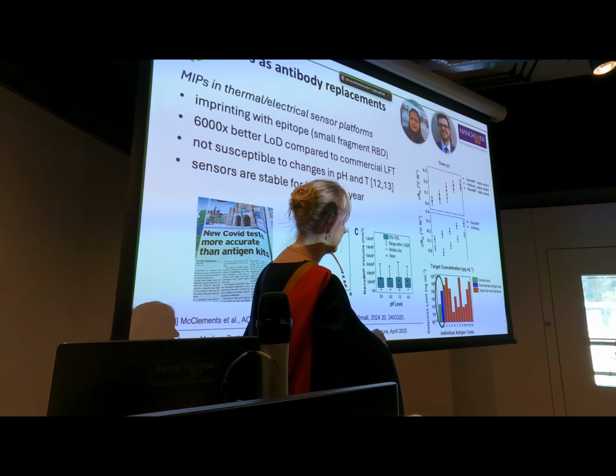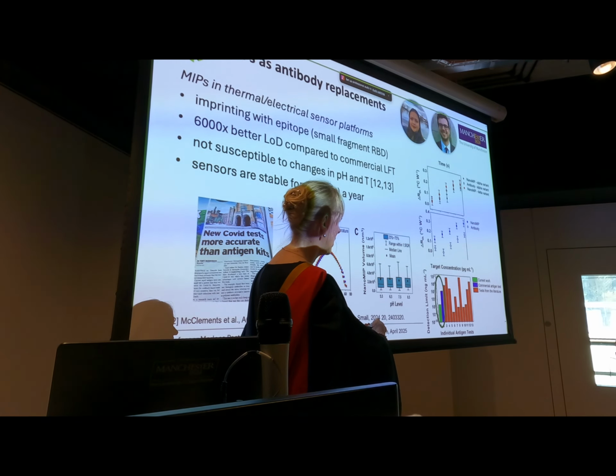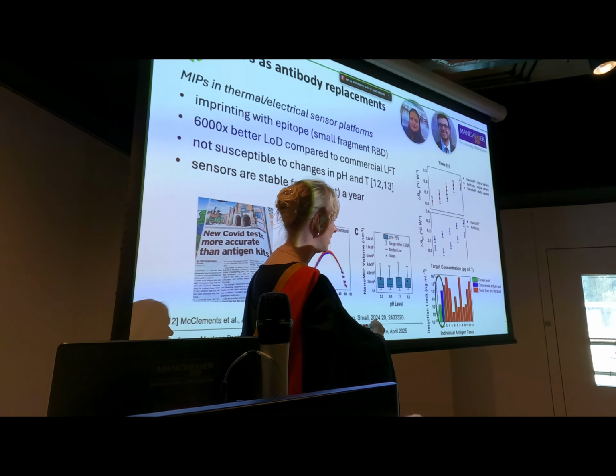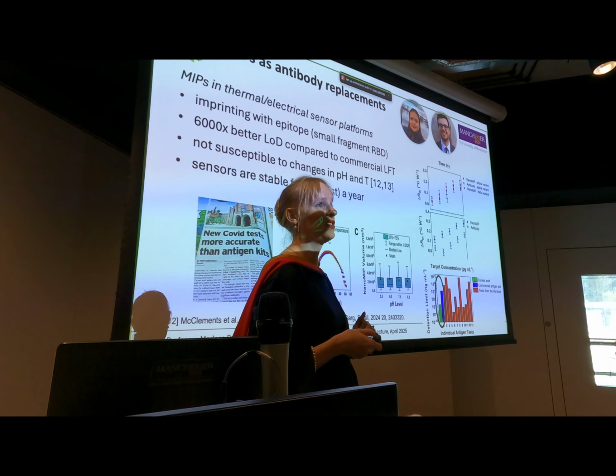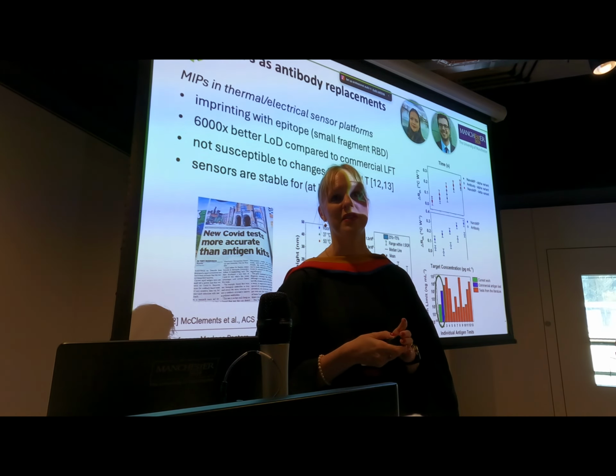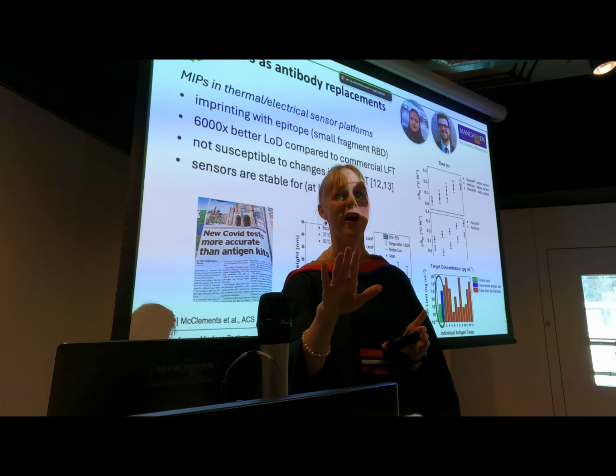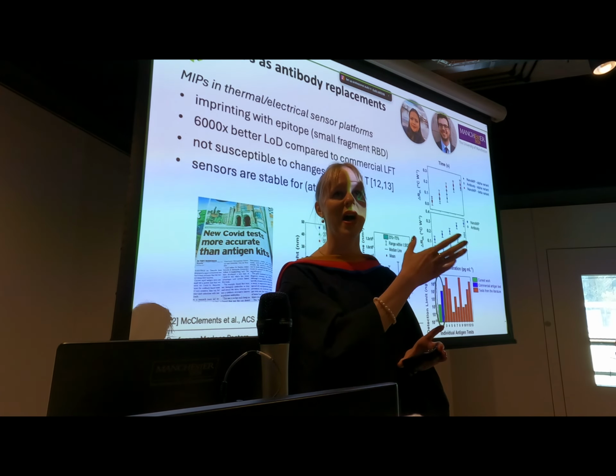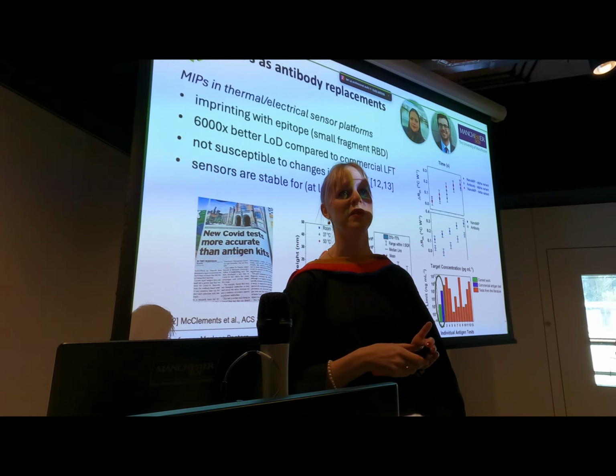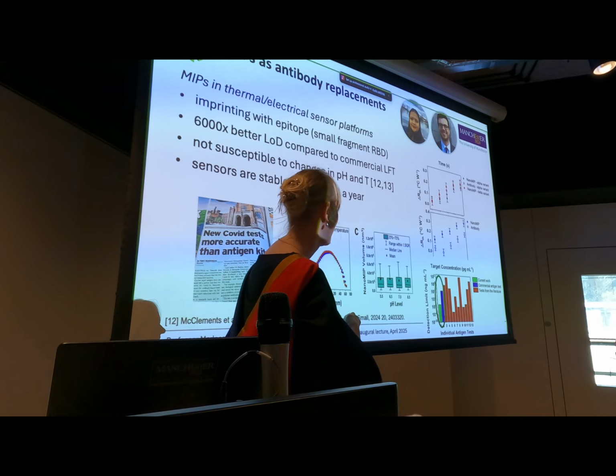And this is the comparison here where we had our test versus the commercial antigen test, so the lateral flow test. You can see it was definitely a lot better than what we anticipated. Obviously not better than PCR, but the advantage here is that you have a test where you get the result in 15 minutes, so much quicker.